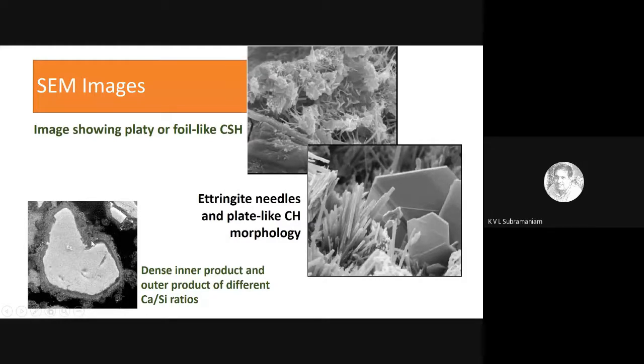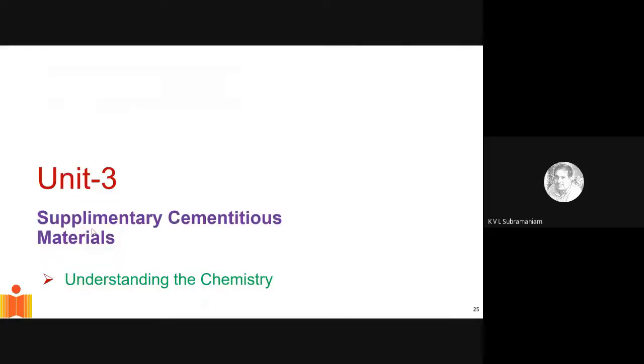If I sample the calcium silicate hydrate close to the cement grain, it will have a certain composition. If I sample the calcium silicate hydrate away from the cement grain, it will have a different composition. And also the way it is packed varies. And this has enormous implications on the final strength, the final properties of the hydrated cement, and also of the concrete. So, a quick touch-up on supplementary cementitious materials.